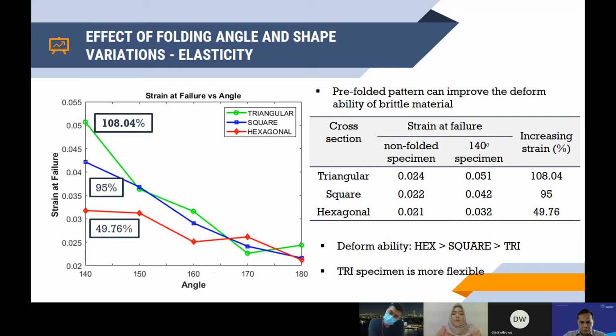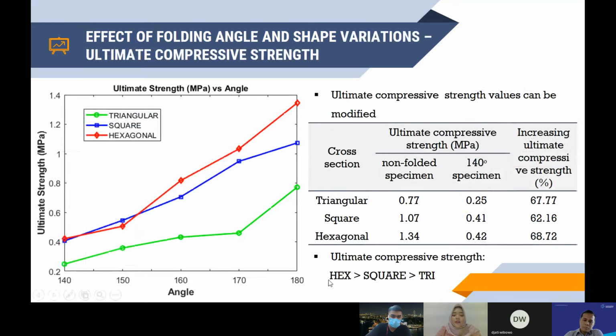As the pre-folded pattern is introduced, we can see that the strain at failure, or deformability, of a structure can be modified into a higher value. Moreover, by modifying its cross-section shapes, we can also change the value of strain at failure or deformability. In this case, hexagonal has the lowest value of deformability compared to the other cross sections. And the non-folded column structure is indicated by 180 degrees.